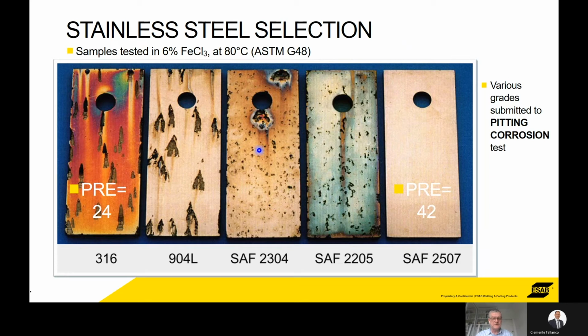So all of these test coupons have been submersed in this nasty solution, 6% ferric chloride at 80 degrees. So it's a reproduction of a G48 corrosion test, a fairly standard corrosion test for stainless steels and duplexes in particular. So you can see over on the left-hand side, we have a 316 stainless steel that looks like it's been very badly corroded. It's corroded on all surfaces, and these things are the pits. So these are massive holes in the surface of the stainless steel.